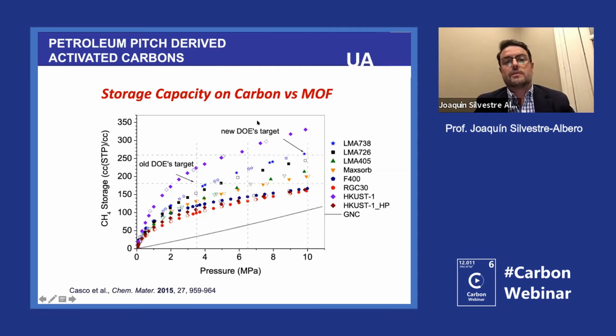And just to end this part, once we reached these values, we wanted to compare with this special MOF that was reported in the literature. In this figure, we compared the MOF, which is the violet, with our best carbon, which is the blue star. And we decided to take these materials and apply 1 ton of pressure, trying to make a conforming step. In the case of the violet, which is the MOF, you can see that the MOF can reach 263 volumes per volume at pressures lower than 6 megapascals. In the case of the carbon, we need, as I told you before, close to 100 bars. But the nice thing is that when we applied this 1 ton of pressure, the violet diamonds went down to the brown ones. So we were destroying the porosity of the system by 50%. However, in the case of the carbon, we applied 1 ton of pressure, measured the system again, and the adsorption capacity was the same.